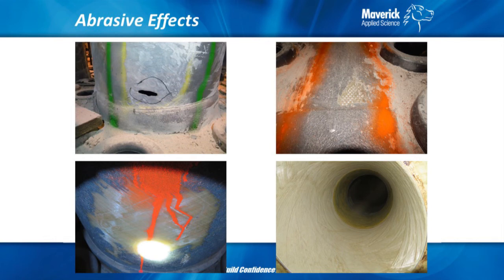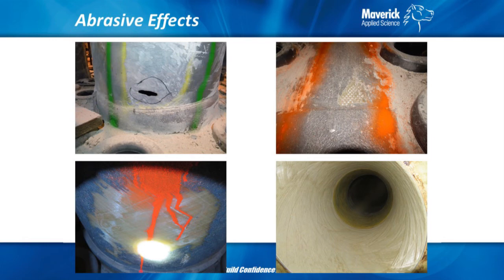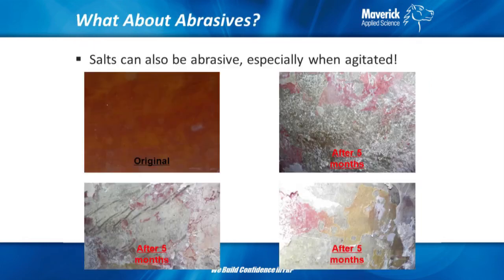If you wear enough to go through the entire wall of the riser, I would say you either weren't paying enough attention or you have an issue with your process that is focusing on certain areas. But yeah, if you see exposed woven roving, that is not a good sign. That means the liner is gone. Right here would be an area where there was abrasion-resistant material, and now there's not. And upon closer inspection, you can actually see some of the windings are gone there too. And this is another example where you can just see bare windings. This is a case where it's just a discharge off of the pump.